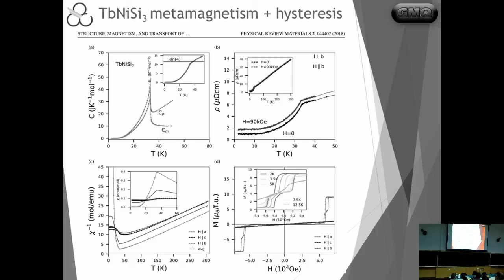And in the case of terbium, when we look at the magnetic transition, we start seeing multiple steps that are coming out and hysteresis. So these are two features that are kind of surprising. We still don't really know what exactly is being involved here. We do have some suspicions. One of them is that we might have, in this case, issues related to nickel vacancies in the system. And this might be causing these types of hysteresis and also the metamagnetic transitions here.